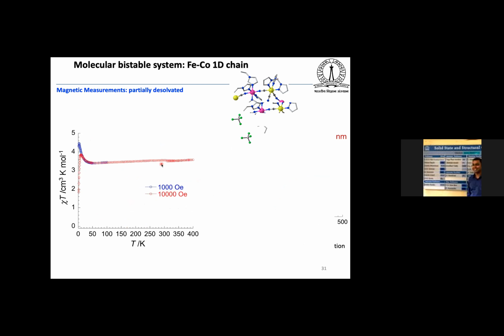And other interesting things happen when you remove the water molecule. We thought, if you remove the water molecule from the system, what will happen? So we got the crystal structure, and you can see there is no solvent molecule present in the system, and the color of the system has also changed to completely red. And you can see the system is completely paramagnetic in nature, and even at low temperature, we do not observe any metal to metal electron transfer.